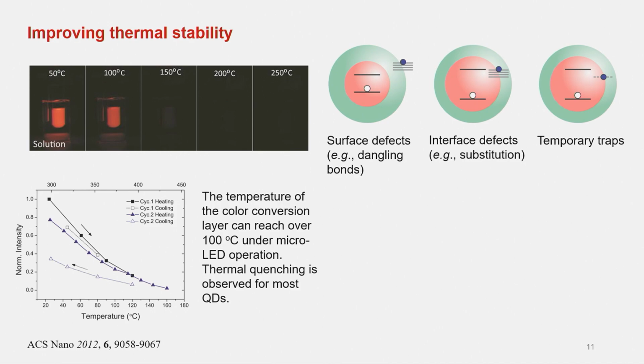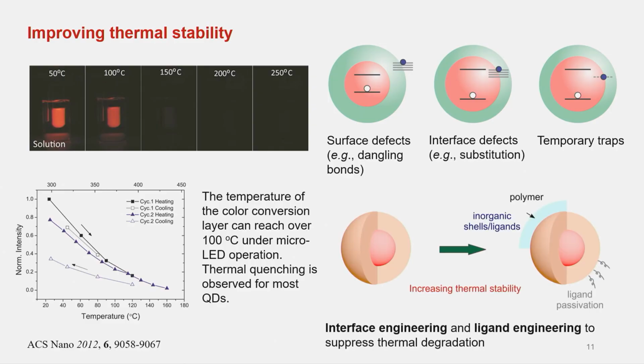You can have surface defects, where the electron will be trapped on the surface, or interface defects in the core-shell materials, where at high temperature you'll have some substitutional defects. Some people argue there are temporary traps that the PL can recover from when back at room temperature. So combined with the spectral studies, we can first understand, for indium phosphide quantum dots for example, what the real mechanism is, and try to find a solution to it.